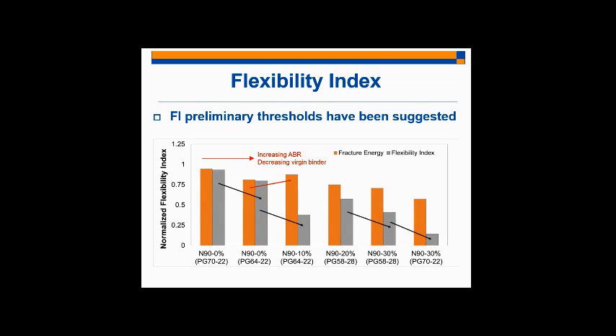And so then we looked at the performance of all of our laboratory mixtures. And if you remember the lab mixes I discussed earlier, we started out with a very, very good parent mixture of an N90 0% RAS, PG70 minus 22. This is, by the way, polymer modified. Then we bumped the binder down to a softer binder, and then we added different amounts of RAS. We're making the mixture worse and worse. And so if we look at the fracture energy results and compare them to the flexibility index values that we calculated for these mixtures, we can see some very important differences.